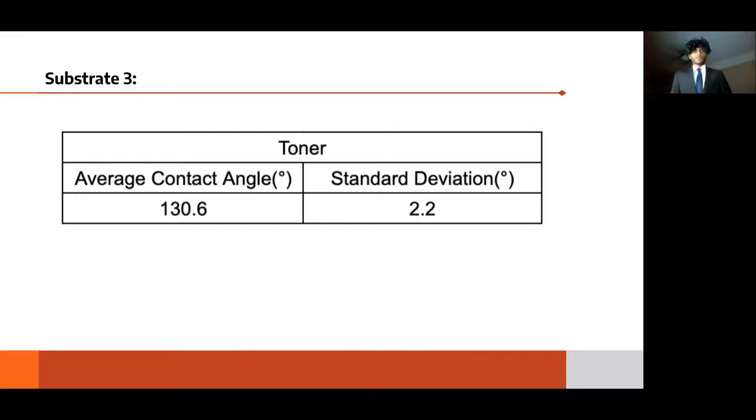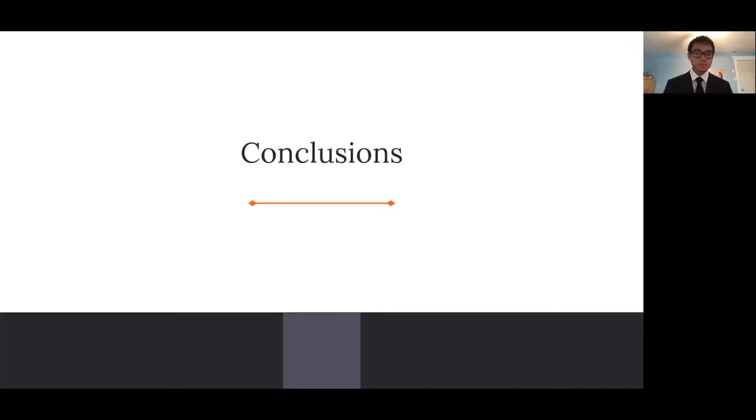When printer toner was lightly powdered on a surface and water droplets were deposited onto said surface, it yielded the largest contact angle out of all of the tested substrates. It produced a contact angle that was greater than the control and the highest sandpaper grade by 163.8% and 121% respectively. The toner proved to be a much more effective alternative to the silicone moldings due to the very small nanoparticles creating air pockets to hold up the water.